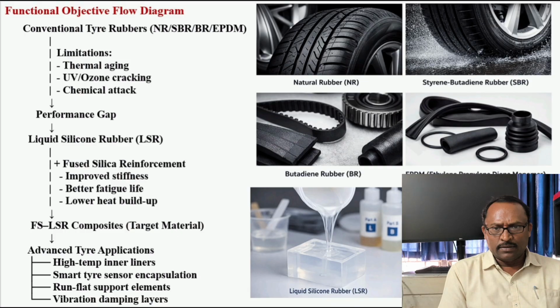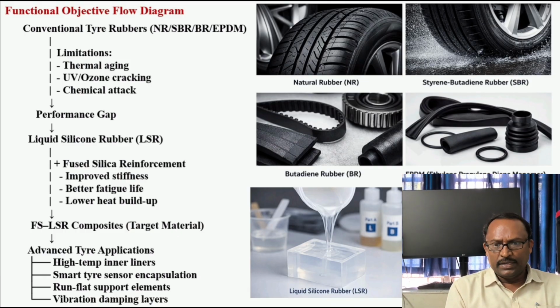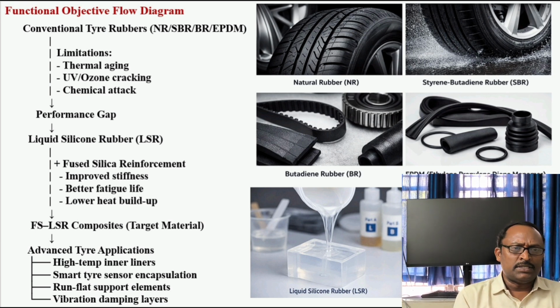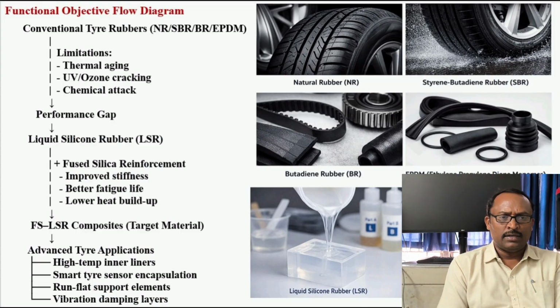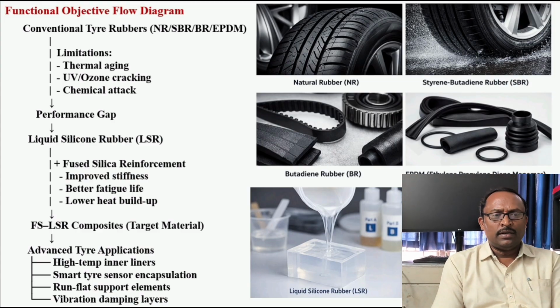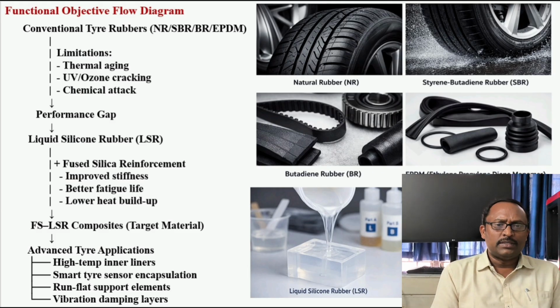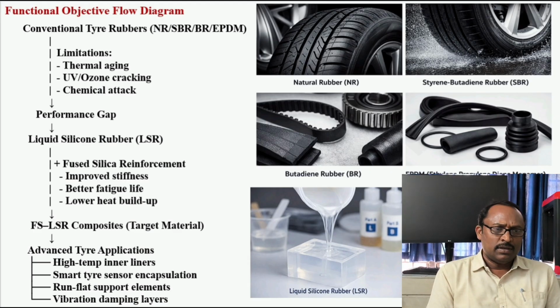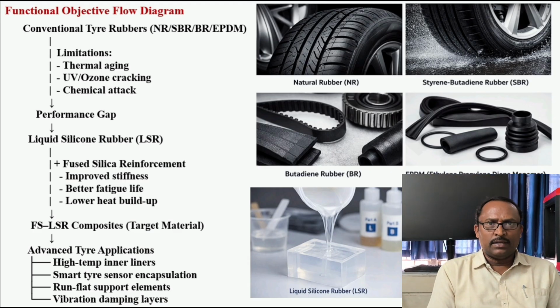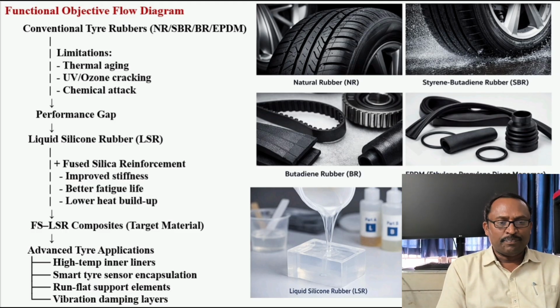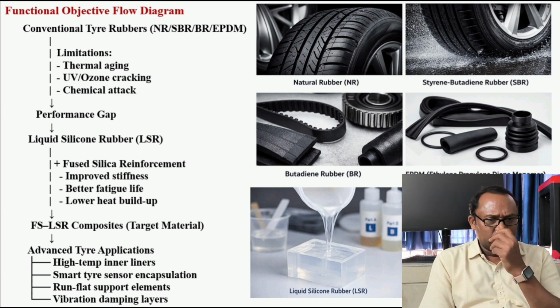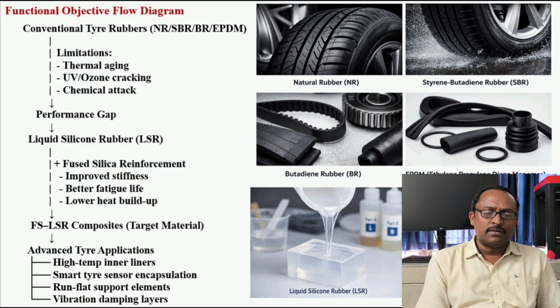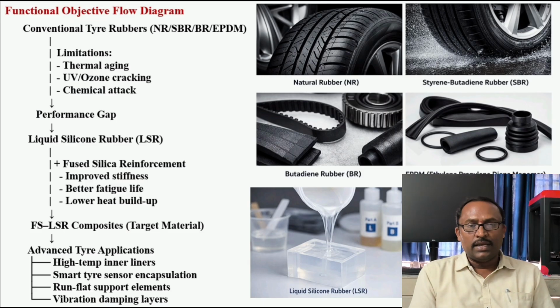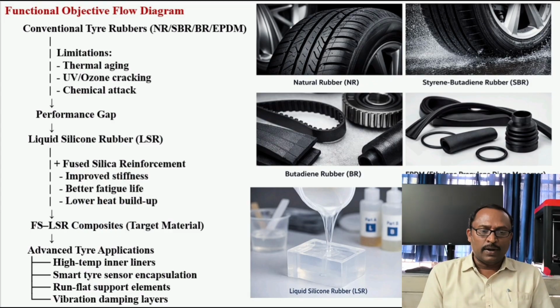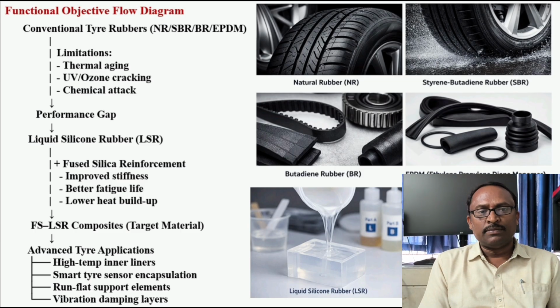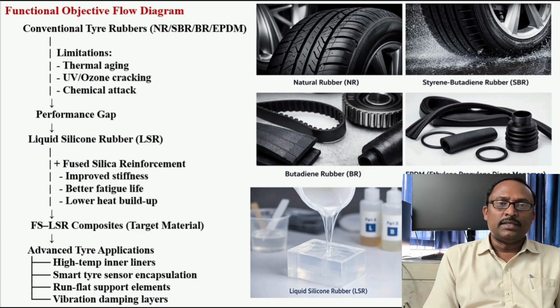The tire which we designed uses natural rubber, styrene butadiene rubber, butadiene rubber, EPDM rubber, and also liquid silicone rubber. Dear friends, the functional objective flow diagram: conventional tire rubbers, that is NR, SBR, BR, and EPDM, have limitations: thermal aging, UV and ozone cracking, and chemical attack. These are the performance gaps, but we can overcome them by using liquid silicone rubber reinforced with fused silica, giving improved stiffness, better fatigue life, and lower heat buildup. So that gives the FS LSR composites. This is our targeted material because advanced tire applications need high temperature inner liners, smart tire sensor encapsulation, run flat support elements, and vibration damping layers. So these are the fundamental requirements, or flow diagrams, for designing the tire material.